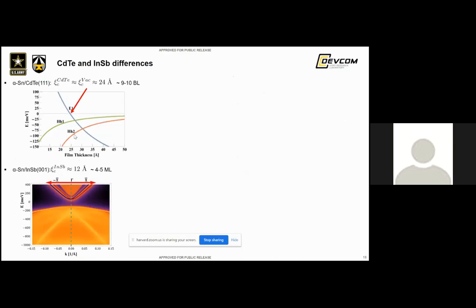Typically, most materials have strong hybridization as soon as you make the material thin enough. So in CdTe, you have a very strong hybridization going on between the top and the bottom topological surface states. In indium antimonide, there's almost no hybridization going on, or very, very small. And that combines to make this critical thickness small, as shown here.